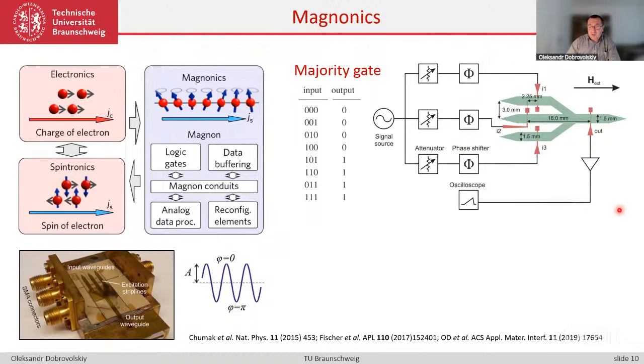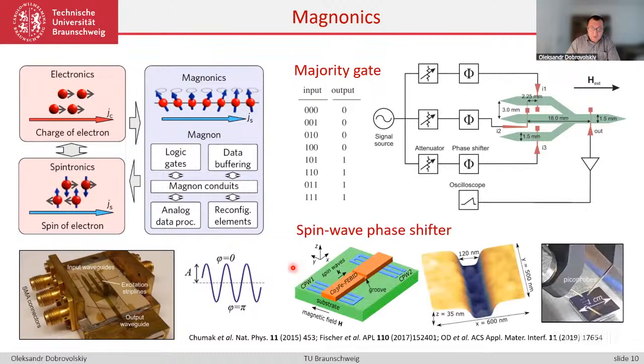And we asked ourselves whether it would be possible to fabricate phase setting elements, phase shifters, which would be nanoscale and integrated on the same chip. The typical geometry here is shown in green. You see a substrate. On top of it, there are two antennas, in blue, one to excite spin waves, another antenna to detect spin waves. Spin waves are excited in a magnonic conduit, which bridges the space between these two antennas. They propagate from left to right.